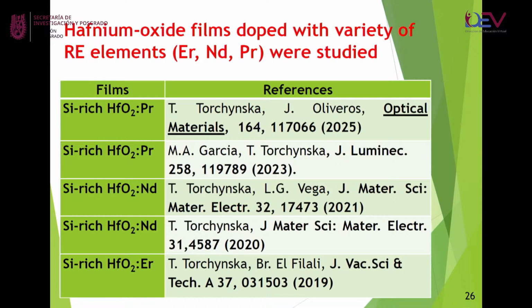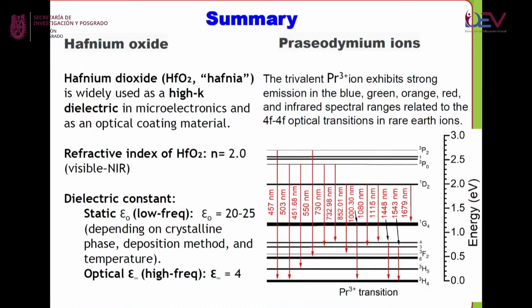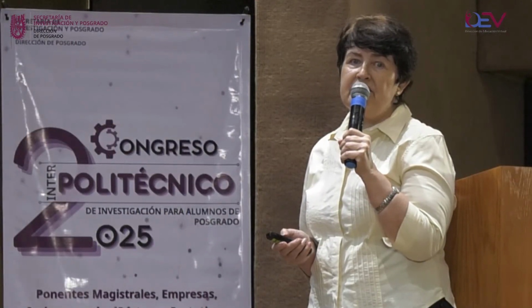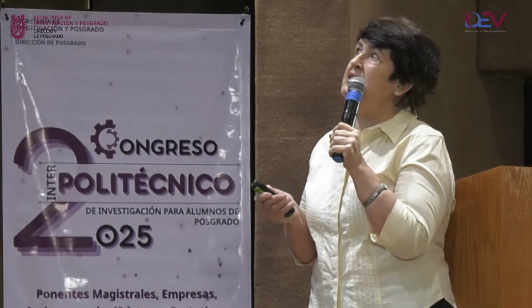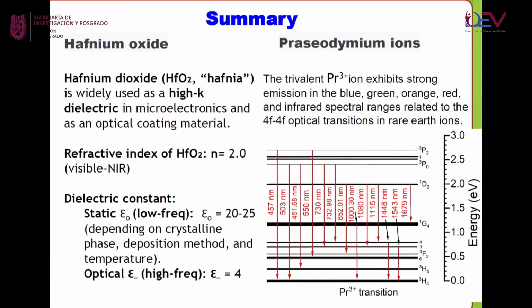You could see here our publication connected with this topic. And right now, I present our result very briefly. Here you could see the rare earth atom praseodymium. As this atom has the electronic shell 4f, this shell separates into different discrete levels when the atom is put in the hafnium oxide matrix. And you could see here luminescence of different transitions connected with the electronic recombination between energy levels inside this rare earth atom.